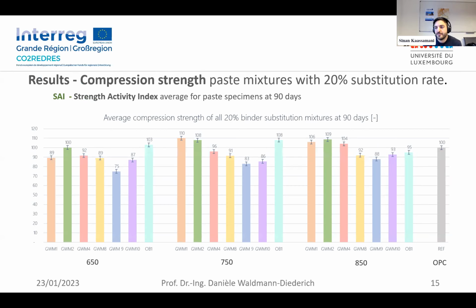And then, last but not least, the compression strength. After analyzing direct pozzolanicity, we analyzed the indirect effect, right? Through mechanical performance. And here we compare the pastes with 20% substitution rate to a reference, which is 100% OPC. And as we can see, some of the materials presented lower strengths, but almost all of them are over the mean of 75%, and even in some cases there are improvements, such as here, 110, 108 for GWM1 and 2 at 750 degrees, also OB1.